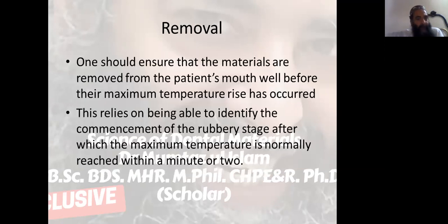Removal. One should ensure that the materials are removed from the patient's mouth well before their maximum temperature rise has occurred. This relies on being able to identify the commencement of the rubbery stage, after which the maximum temperature is normally reached within a minute or two.